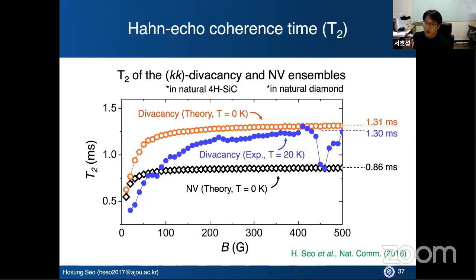That long coherence time is due to basically two things. First, in this sample the dominant decoherence source is nuclear spins again. But there are only 1.1% nuclear spins in the lattice, which is low, so there are not many paramagnetic spins nearby. And you can also make a more dilute nuclear spin bath by isotopic purification. Then your coherence time becomes even longer.